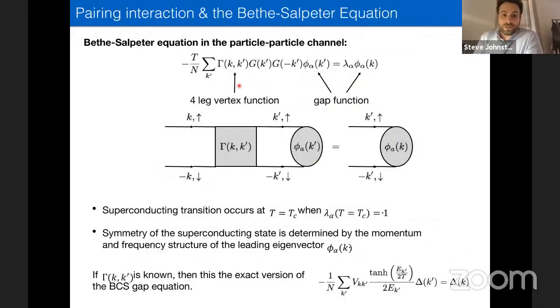The reason we're using this DCA++ code is that over the years, there's been a lot of development effort put into measuring this generalized 4-point vertex function. You can think of it as this diagram that I'm showing here. It's all the ways in which pairs of electrons can scatter by interacting via the Coulomb or the Hubbard U in the system, all calculated non-perturbatively. So this can be measured with DCA++. The Green's functions can be measured with DCA++, and that allows us to solve the Bethe-Salpeter equation in the particle-particle channel.